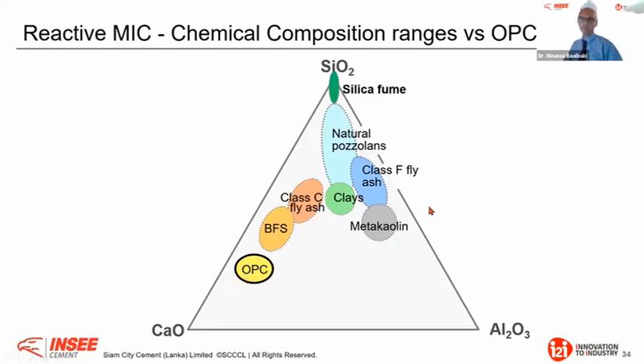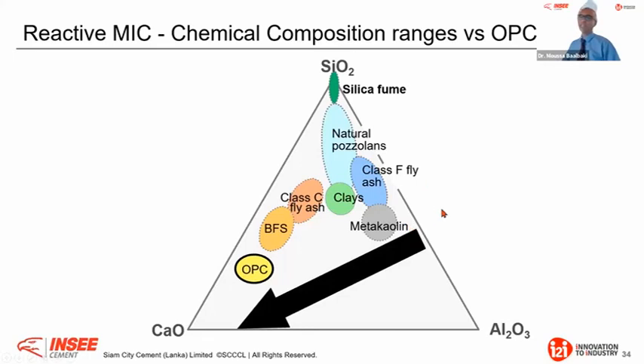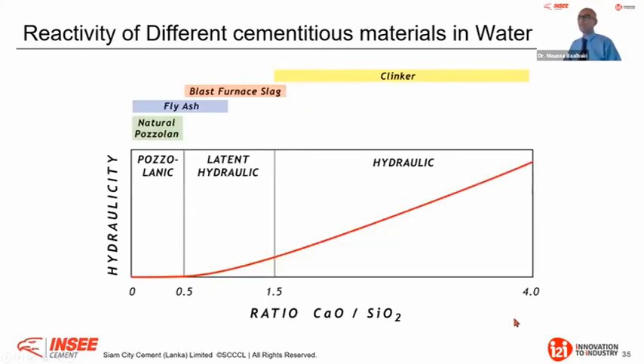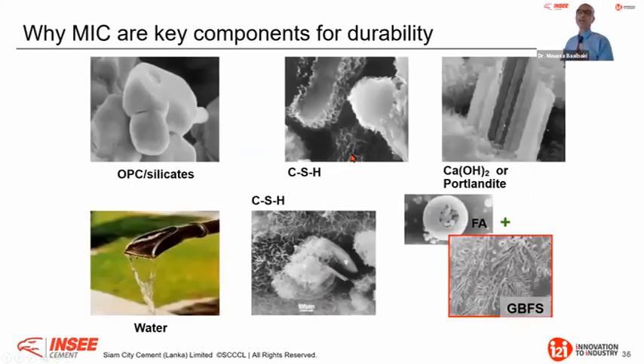And you have the aluminosilicate ones. These aluminosilicates are not reactive, like for example silica fume, a very noble mineral component, but silica fume alone is inert. Any of this material is inert, therefore you need to activate them. The activation comes through calcium, because they have the silicon. This is why when we look at the calcium silica ratio, from pozzolanic material where basicity is below 0.5, to latent hydraulic between 0.5 and 1.5, and above 1.5 we come to hydraulic like clinker. And very often I say clinker is above 2. And this is what it comes to when it comes to hydration.